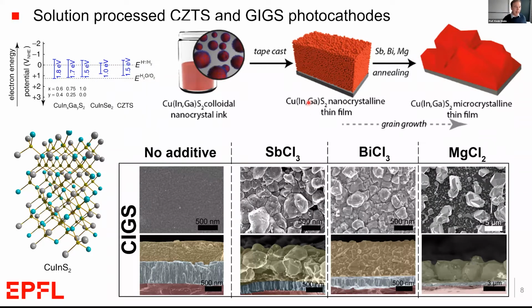So just to give you some electron microscope images to show you how we do this, here's a cross-section of a film showing our nanoparticle CIGS layer before any annealing and without any of these special additives that help reduce the sintering temperature via a eutectic effect. But when we add this antimony, bismuth, or magnesium chloride, we can grow these crystals at relatively low temperatures and make large microcrystal particles that reduce grain boundaries, reduce recombination of the photogenerated carriers, and improve the photocurrent that we get out of the device.